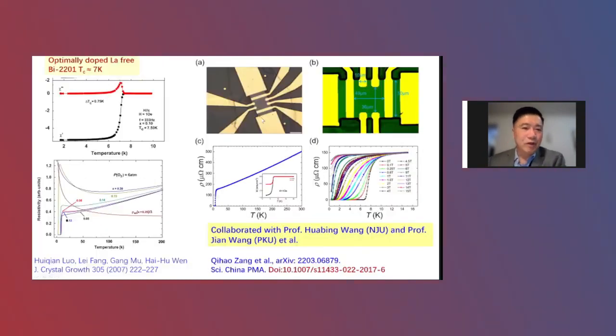And we want to measure more precisely. So we fabricated our single crystal into this bridge, with a very well-defined size and thickness. And for this sample, it's good because the Tc is quite low, so even a lab magnetic field can suppress superconductivity completely.